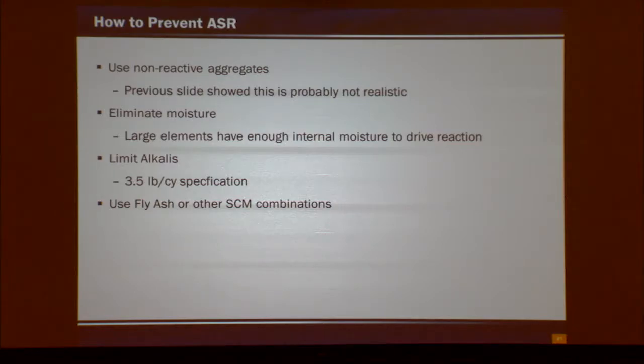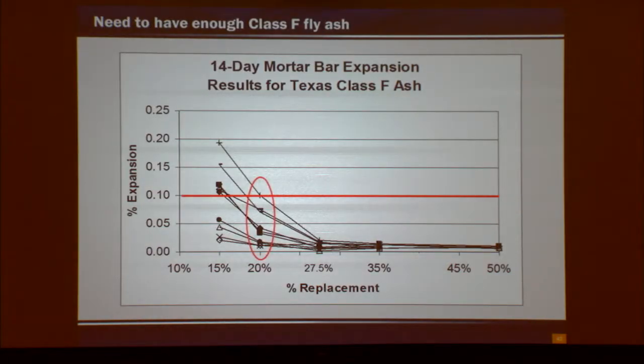We've done a lot of work to make sure those options work. So just keep that in mind when they come up to you and say, hey, I don't have fly ash. Can I put 800 pounds of cement in there? Like, no, that's not what we want. You have to have the right amount of ash. Again, this is our F ashes. And hey, 20%, what's our minimum? 20%. So I mean, we just didn't pick that out of the air. We actually have some data showing that's where we need to be for ASR mitigation for most of our aggregates in Texas.